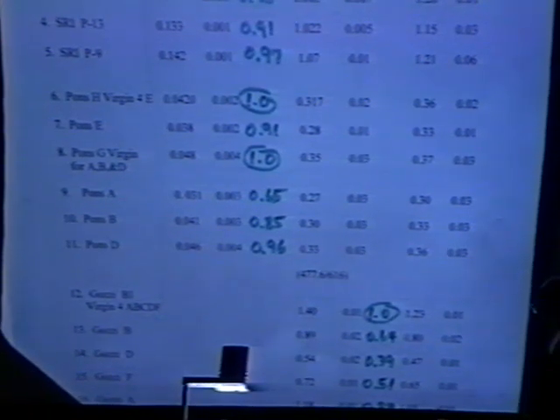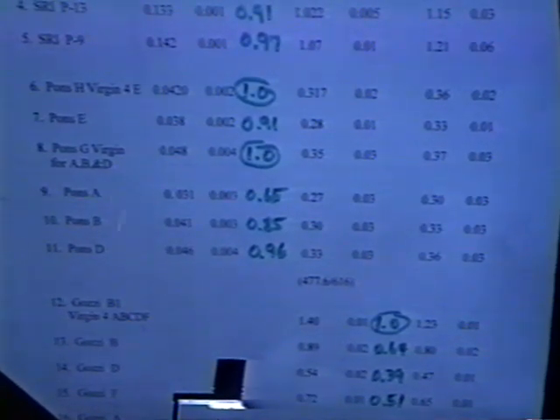Again, he had a virgin material here for 3 2-millimeter cathodes. This is a 4-millimeter cathode. And again, we have a very remarkable 35% reduction down to 0.65 of the boron in that one, 15% there, and then barely 4% there. So we'll see if those, when I finally find the amount of heat involved, correlate with that.